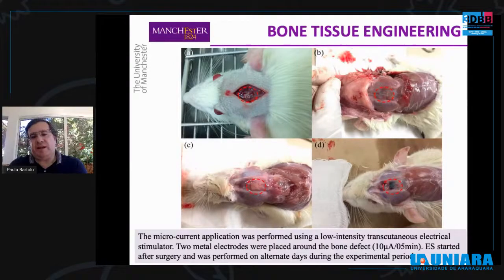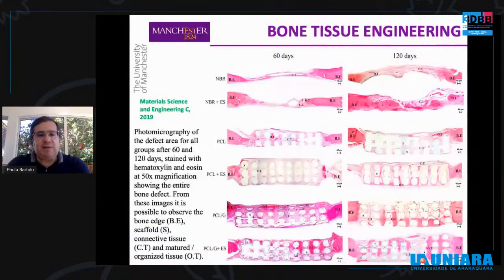And finally, we filled the defect with electroactive scaffolds, PCL scaffolds containing relatively small amounts of graphene, around 1%, and again with and without electrical stimulation. The photomicrography images of the defect are presented in these slides, and the results show that in the control case, so the natural bone regeneration, it was possible to observe the formation of a thin connective tissue, and in the case of applying electrical stimulation, the presence of pockets of new bone at the edges of the defect, across the edges of the defect.